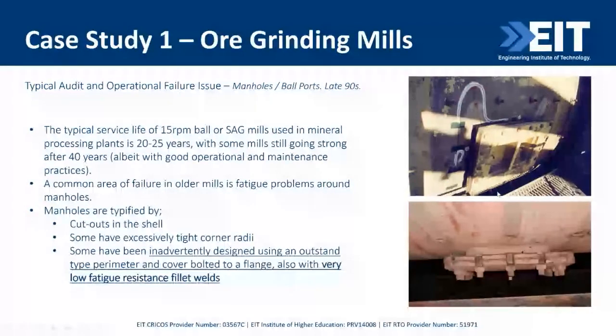So this is a bit dated, but some of the early mills had poor manhole cutouts in the shell, with the rectangular cutout in the shell for the manhole for access, with too tight a radius and a poor outstand fillet welded cover. So this is the manhole cover bolted onto this outstand fillet welded arrangement. So the rectangular cutout with too small a radius exacerbated by the fillet welds, and you've got cracking. You've got cracking at all 4 corners.